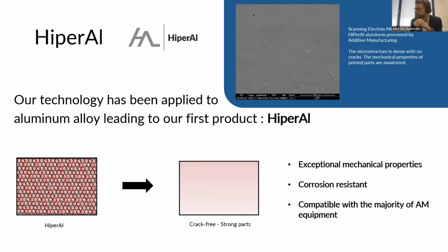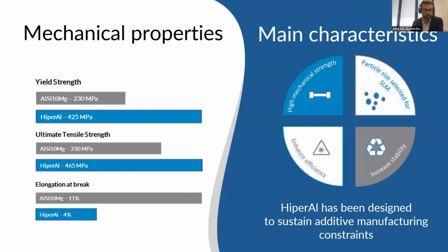Basically, it's the microscope images also on the top. You can see that there are no cracks anymore. Porosity is really decreased. We obtain exceptional mechanical properties. We keep corrosion resistance, and it's compatible with the majority of additive manufacturing equipment. If we look a little bit deeper at the mechanical properties, which is really interesting with the 7000 series, if we compare it to the classical aluminium printed right now in the additive manufacturing field, we are nearly 2 times stronger in terms of yield strength and UTS.